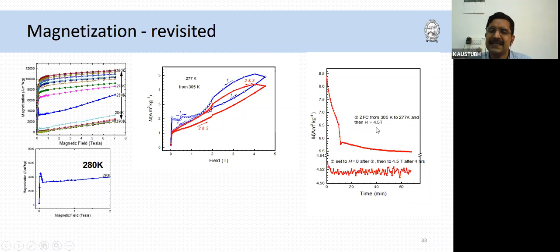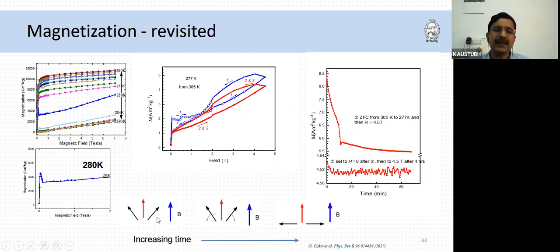So we measured the relaxation times also, and we came to the conclusion that when we apply the magnetic field, all the three spins that we saw in the neutron diffraction, all the three manganese spins, align ferromagnetically, but with time, two of those spins flip to give you an antiferromagnetic order, whereas the third one continues to remain ferromagnetic. So that is the reason why you could see the two spins in neutron diffraction as antiferromagnetic order and ferromagnetic order. So this was the interest with which we tried to understand from EXAFS.